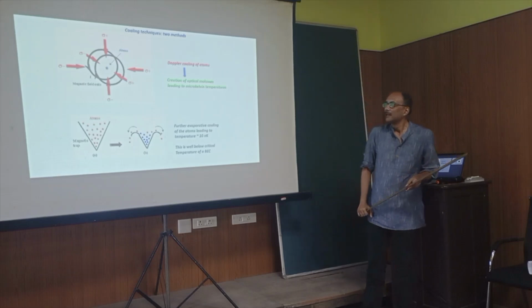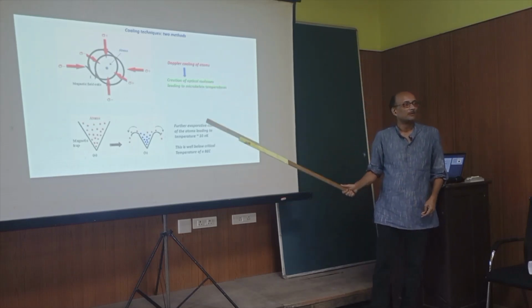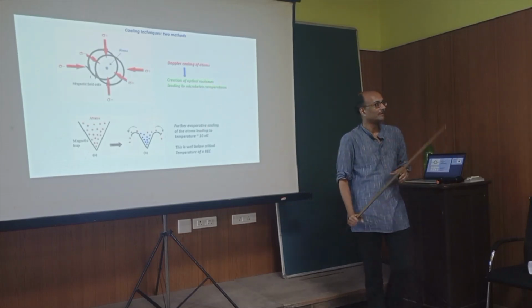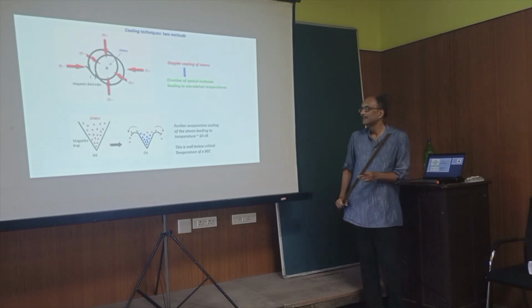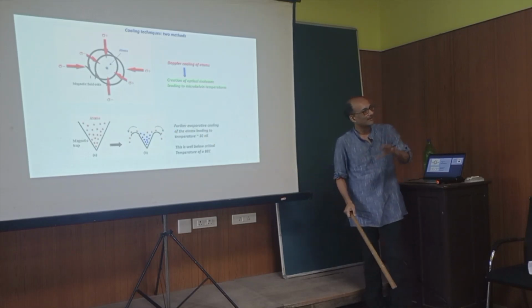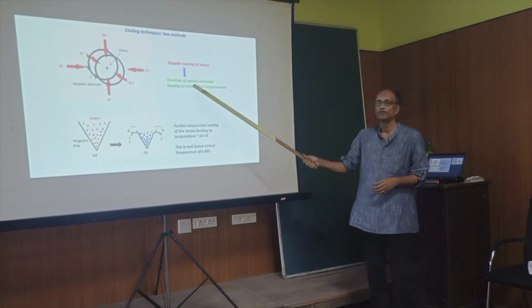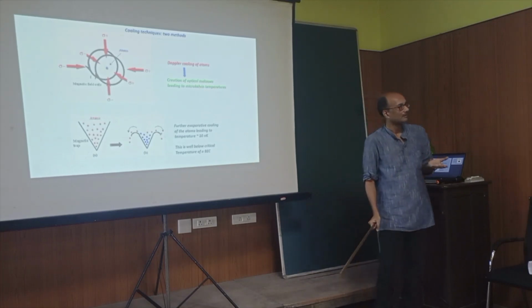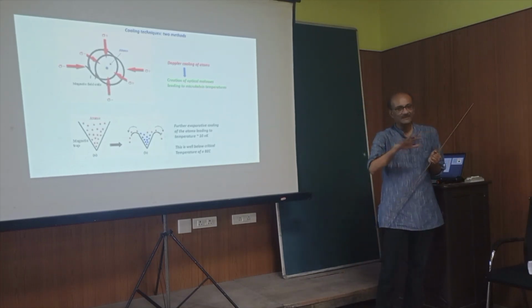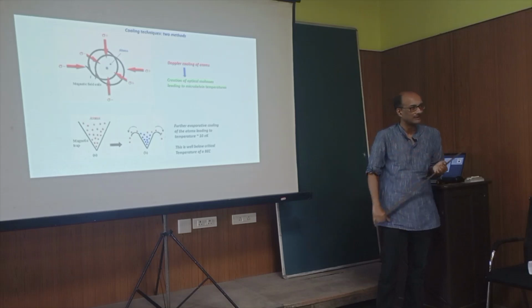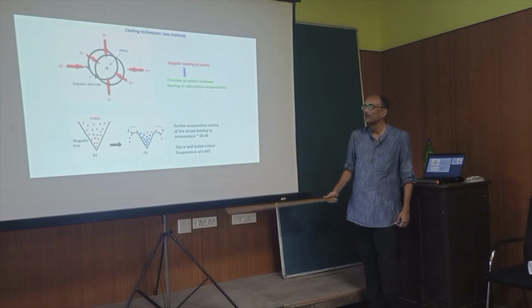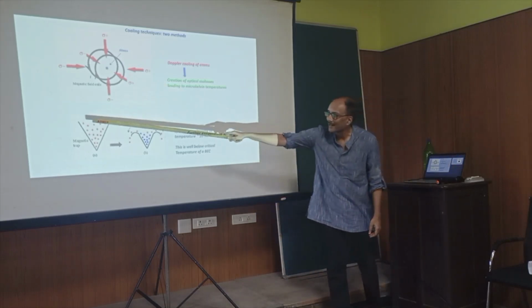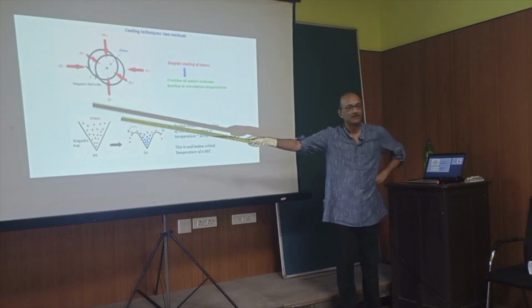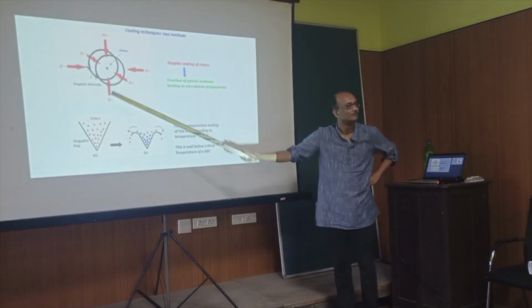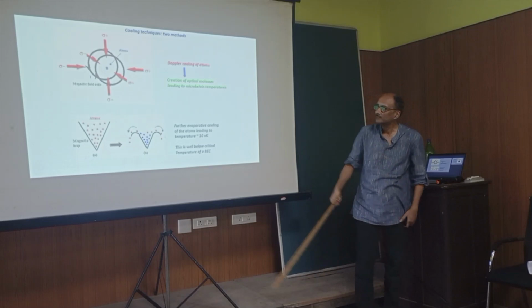Okay. Now, after this, people do another thing, which is also very interesting. And this is really required to get into the nanokelvin range of temperature. This takes you up to a few microkelvins, but after that, everything saturates and you cannot really cool anymore. And then what people do is that they put these atoms, these microkelvin temperature atoms, into a magnetic trap. It's a trap like this.